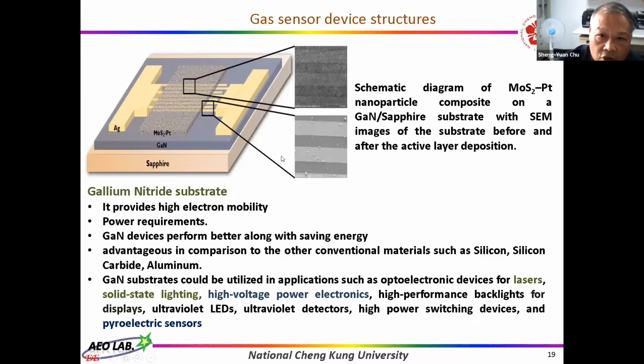This figure shows the schematic diagram of the MoS2-Pt nanoparticle composite on a gallium nitride substrate, with SEM images of the substrate before and after the active layer deposition. Why did we choose gallium nitride as a substrate? Because it can provide high electron mobility and low power requirements.